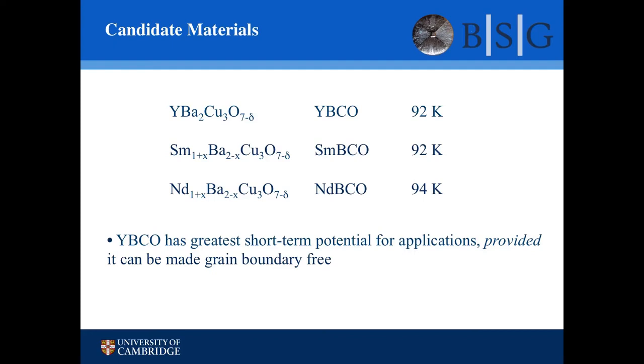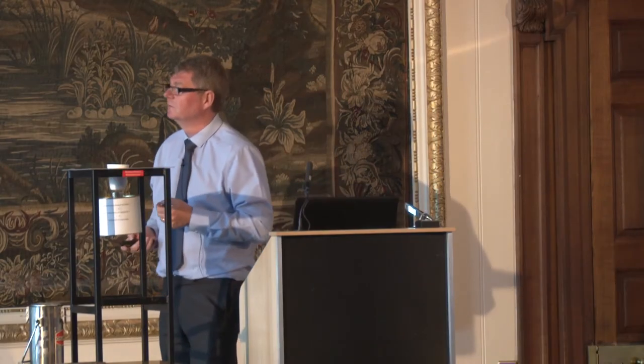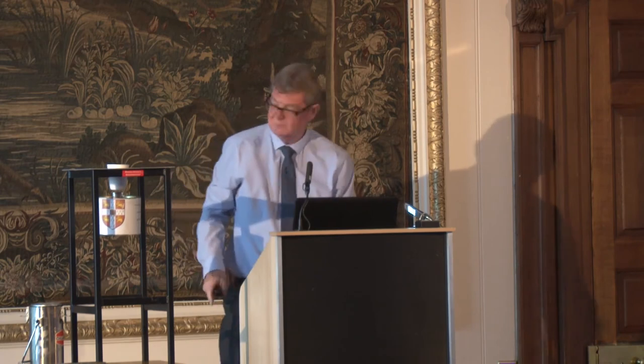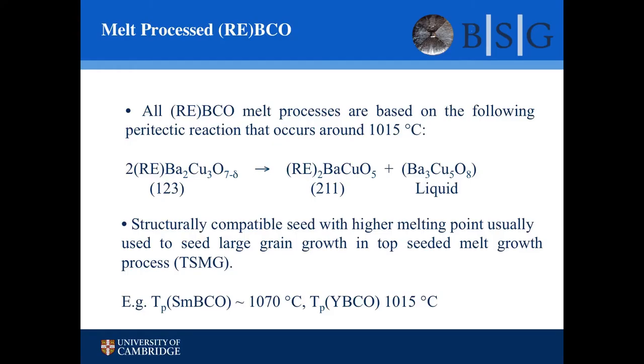But YBCO, ironically the first material to be discovered with a TC above the boiling point of liquid nitrogen, really shows the greatest short-term potential for applications, but you've got to be able to make it grain boundary free. This material here, you see this thing still levitating, suspending, is yttrium barium copper oxide. So how do you go about making it grain boundary free? And you can see the logo here of the Bulk Superconductivity Group.